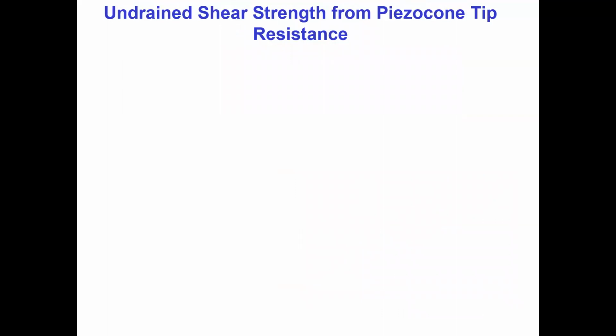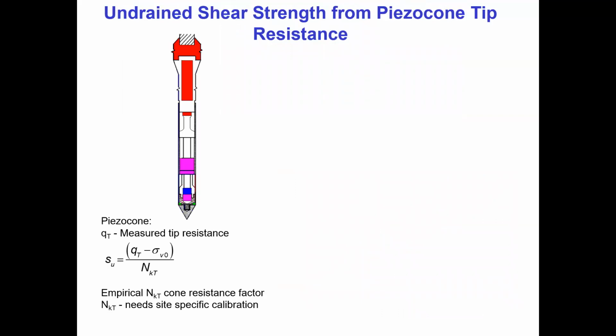For the tests in clays, these are cones in clay. We know that if we push a cone in a low permeability material undrained, the undrained strength is proportional to the net cone resistance. Net cone resistance being the measured tip resistance minus the total vertical stress at the depth. And the correlation coefficient is a cone resistance factor, NK.